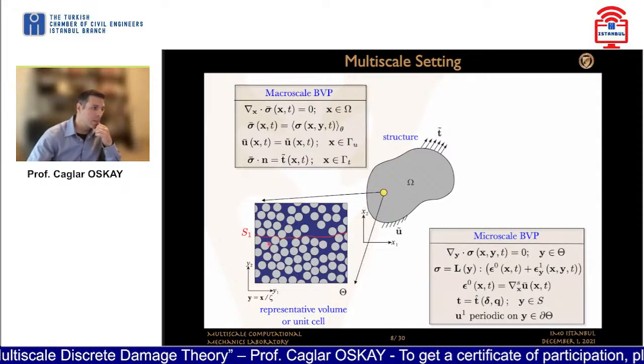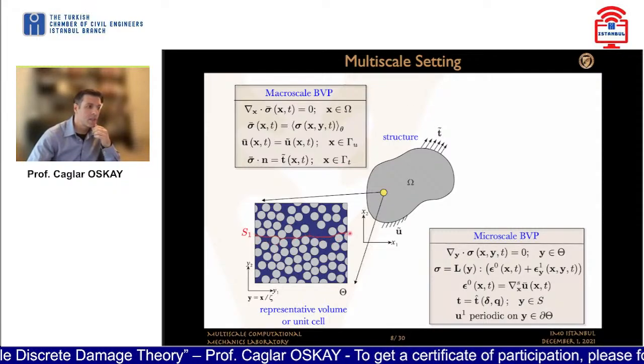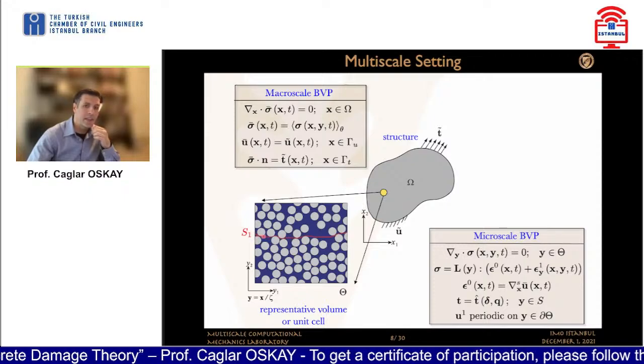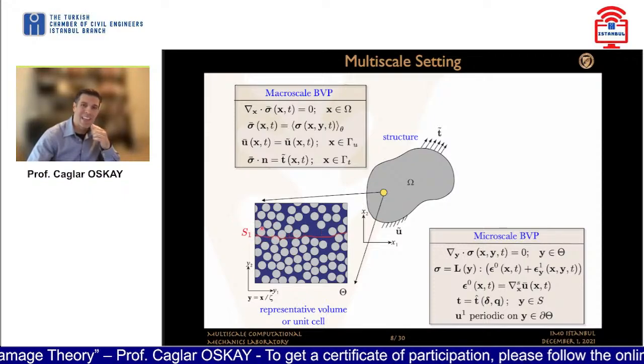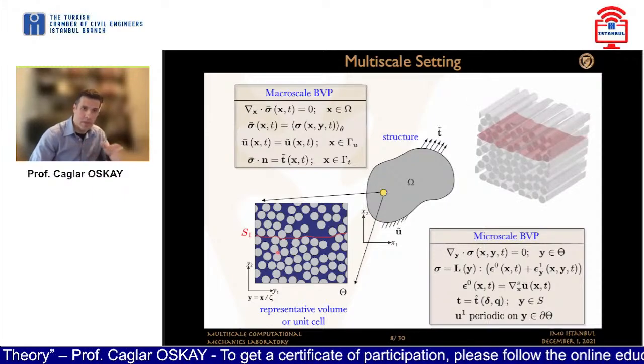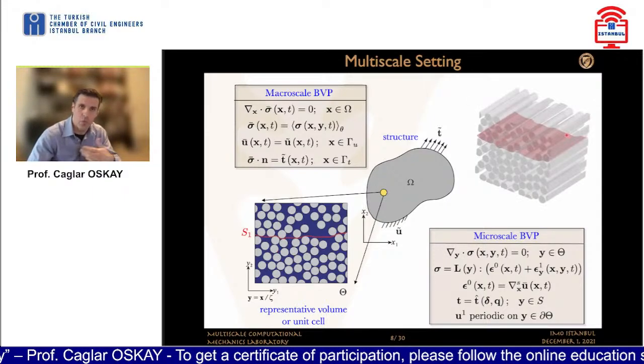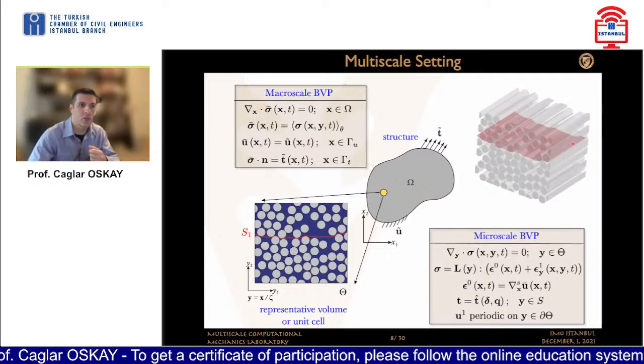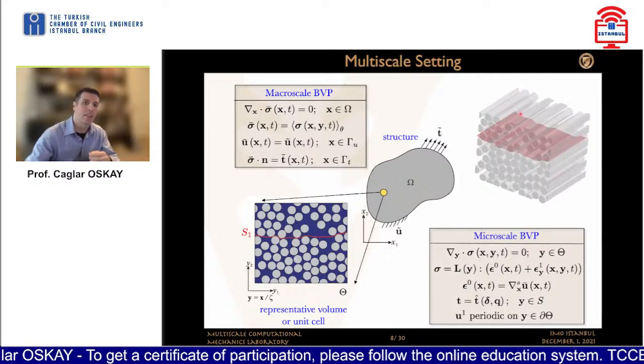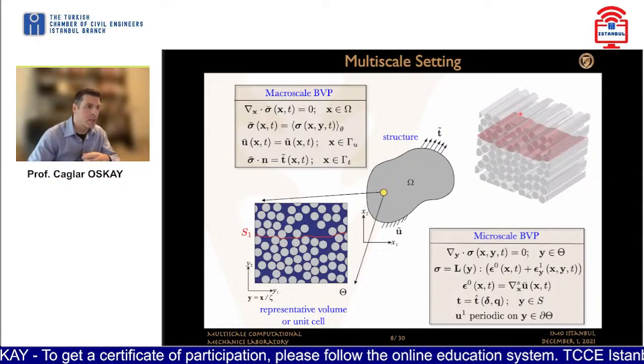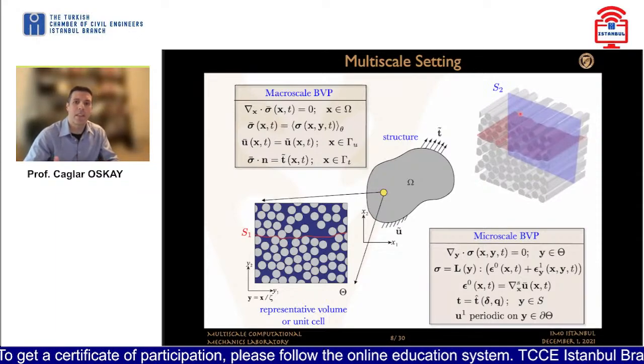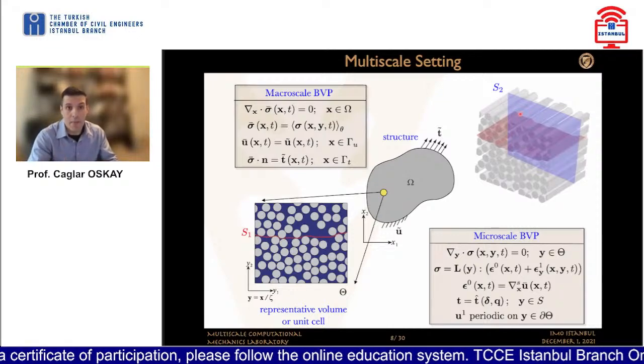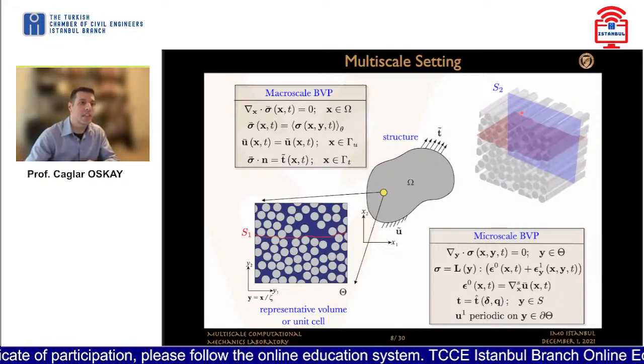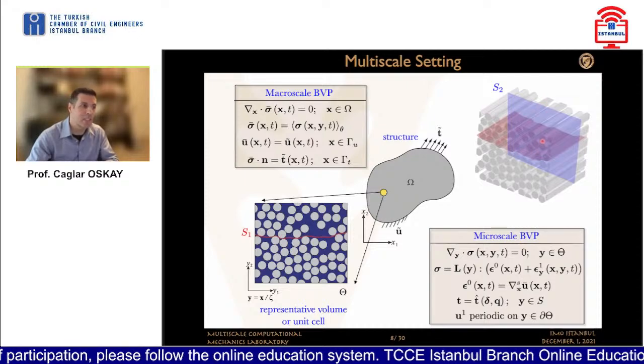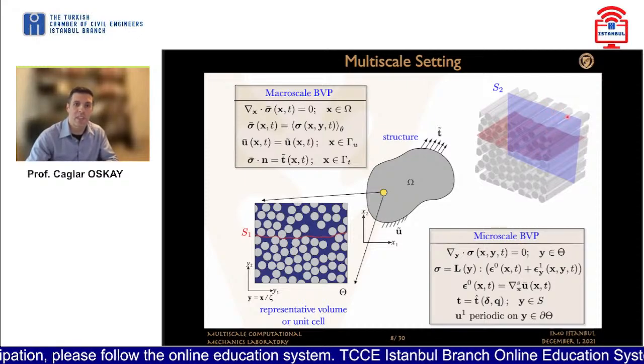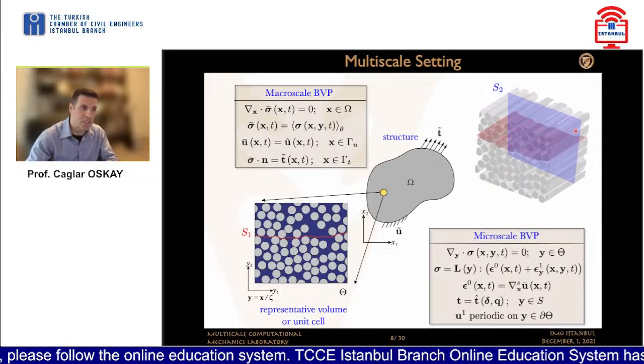Let us call the first crack that you see a matrix crack that occurs, and let's call the morphology of that crack S1. This is, of course, a three-dimensional crack, so you need to incorporate this in a three-dimensional fashion, so you see a surface, that is the crack surface that shows at the microscopic scale. Now, if you continue to load this, there could be another type of damage that could occur. In this case, let us say that nearby this initial micro crack, we start seeing fiber cracking that also starts to develop.